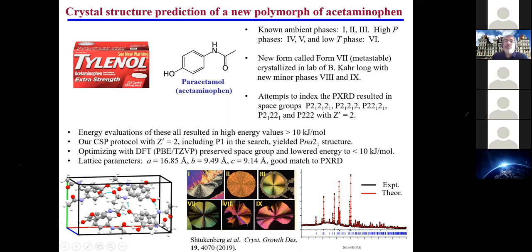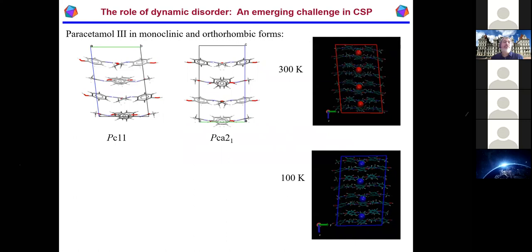But when you start to study some of these other polymorphs, that's fine for one where you can do this. But if you look, let's say, at this number 3 polymorph, this one turns out to exist in a couple of different structures that involve a certain amount of disorder. Now, 3 can either be monoclinic or orthorhombic, depending on temperature. And in fact, it turns out that you have 2 different space groups. So this one polymorph actually is kind of itself multimorphic.